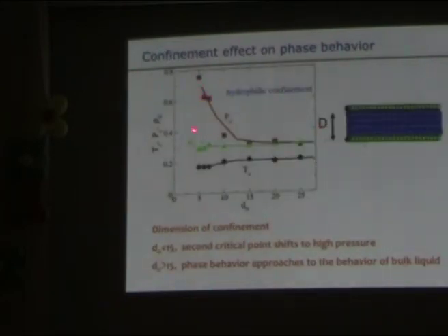Okay, and then here's the critical point that we determined by the end of the Widom line that I mentioned to you. Here, this one is determined by the compressibility maximum. You can see that for different ways of confinement, for instance, if it's extremely confined, 5 or 8, it's just less than 5 layers of liquid in between these two plates. You can see the critical point. Just look at the critical pressure. This is really far off. Okay, so this is a really high pressure, and then of course this is for the bulk case.